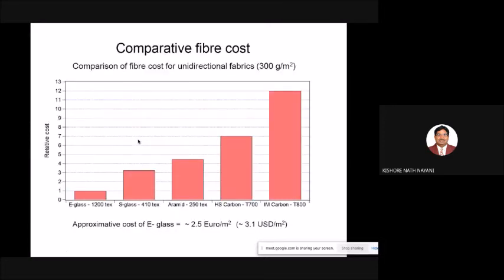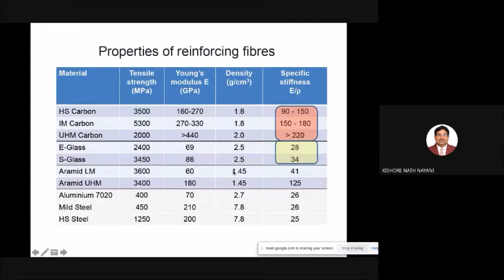If you see cost-wise also, carbon is very costly comparatively to glass. Glass is very low, then S-glass, then aramid, then intermediate modulus and high-strength carbon fabric. When you see the strength levels also, carbon fiber has very high specific stiffness compared to the other materials. You can see as high as 5,300 we can go. But E-glass will have mostly half of the strength. Density is also lower for carbon compared to glass. Aramid is still lighter, but aramid has some issues like moisture and other problems, and availability is also a question mark.